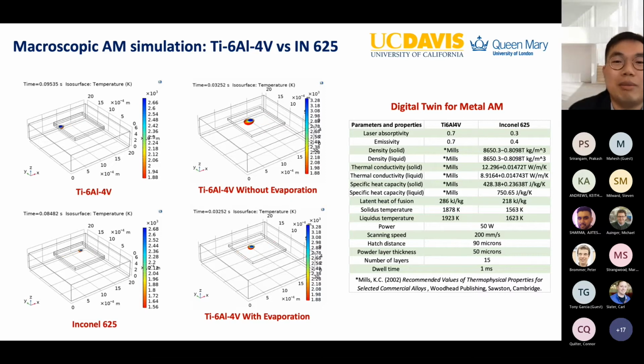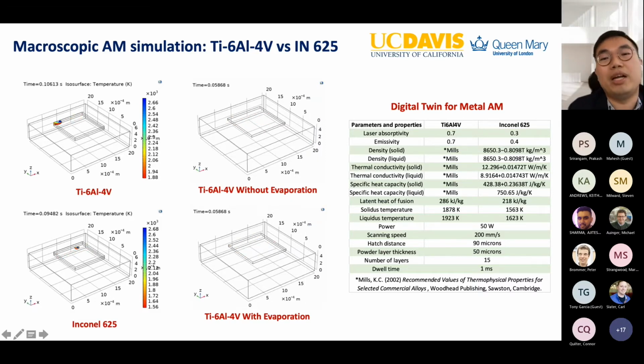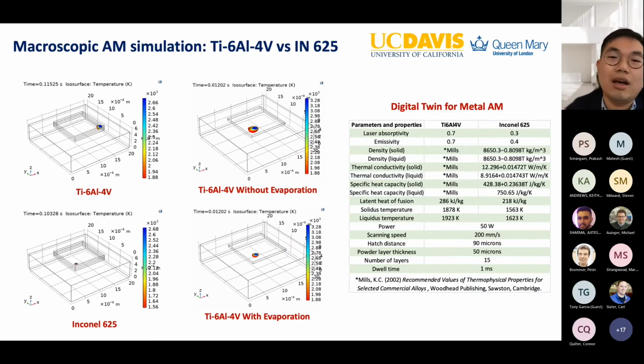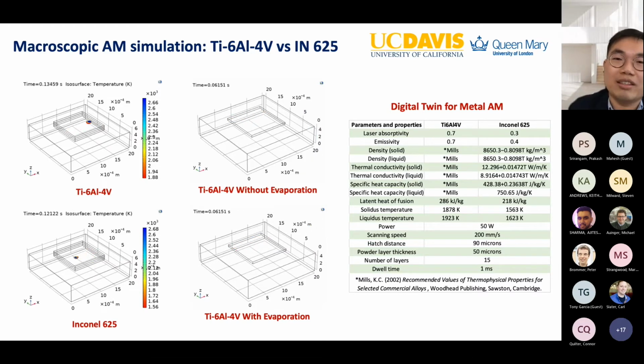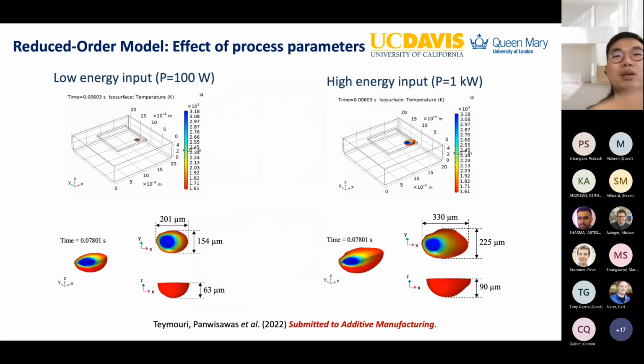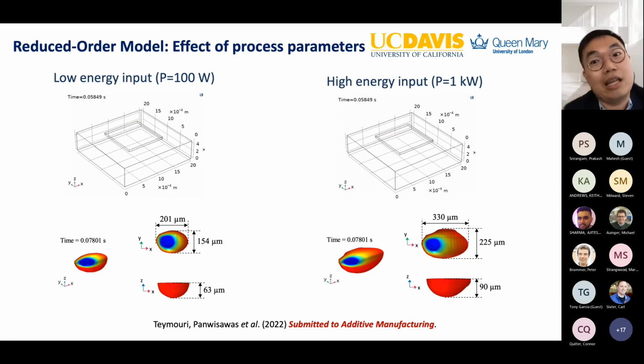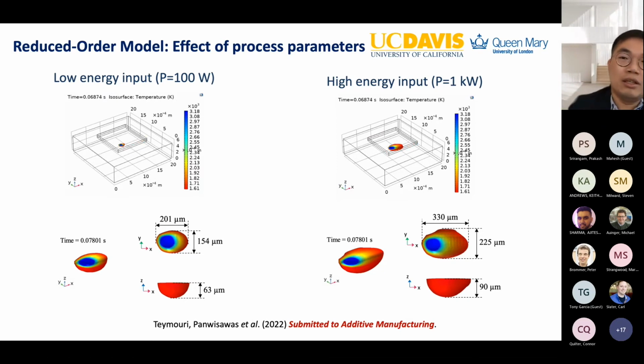So this gives you an example like Ti-6Al-4V with and without evaporation. You will see that the melt pool predicted is rather different. And once you're building up in height as well, you won't be able to get a steady state melt pool, by the way. And this is why we want to develop this kind of model, but it's still not very cheap computationally anyway, but it's cheaper than this high fidelity model, and can give you some kind of predictive capability for further upscaling or further digital twin type of model. So this can quantify that model, capture some physics of prediction that you may anticipate from experiment.